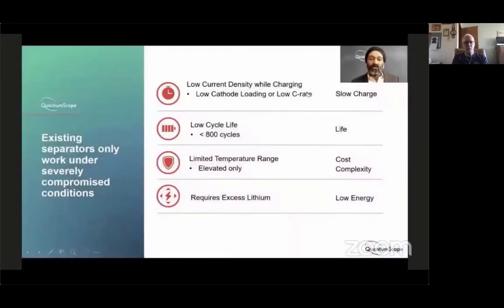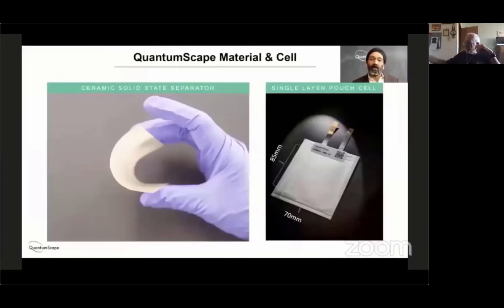Okay, so the quick summary is if you have a material that doesn't have the fundamental entitlement to serve as a solid-state separator, you can still make batteries out of that material, but they only work under severely compromised test conditions. And the main compromises that people use are either very low current densities, which ends up not being useful for real applications like driving a car, or the cycle life ends up being very short, or the cells can only work at an elevated temperature, or they require excess lithium, which lowers the energy density of the cell. These are the problems that QuantumScape has addressed.